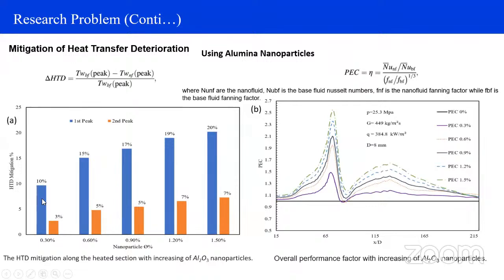So temperature variation is more favorable at the first peak, because at the first peak the temperature is higher as compared to the second peak. Same like when we increase the nanoparticle percentage inside the base fluid to 0.6, then the temperature reduced 15% at the first peak and 5% at the second peak. Same like we can see for other concentrations of nanoparticles, the other concentrations of nanoparticles are also useful to reduce the temperature.